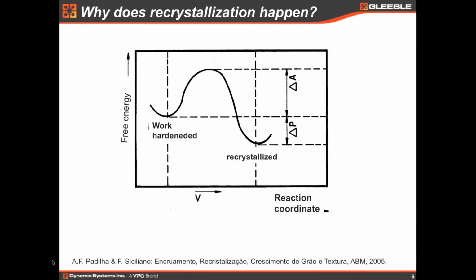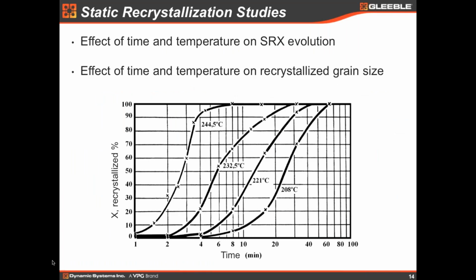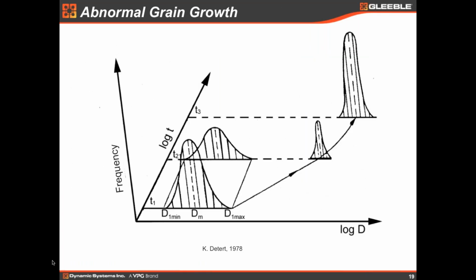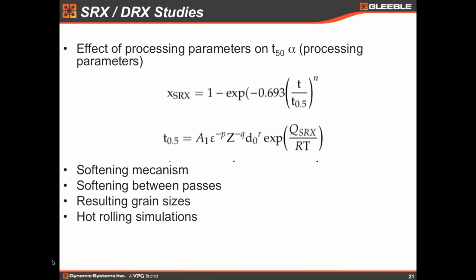Yeah, let me cover that. We can use 20%, we can use 50%, we can use 70%. The reason to use 50% is that it's easier to reach 50%. It's not the very beginning. If you say it's 5%, it's more difficult to catch that in a microstructure. But with 50%, everything that you have to change is this parameter here, because this is the natural logarithm of, I have the exact formula here. Let me check. I have my thesis printed here. So this constant here is because it's 50%. If it's 20%, we just change this constant, but it will have the same effect.